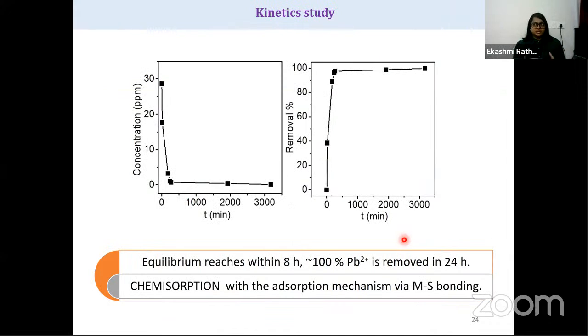Then we wanted to understand how fast this material can capture lead. Here you can see that it can capture lead 100% in 24 hours, and the equilibrium is reached in just 8 hours. And we saw 100% removal of the lead. This happens due to chemisorption, with the adsorption mechanism via metal-sulfur bonding.